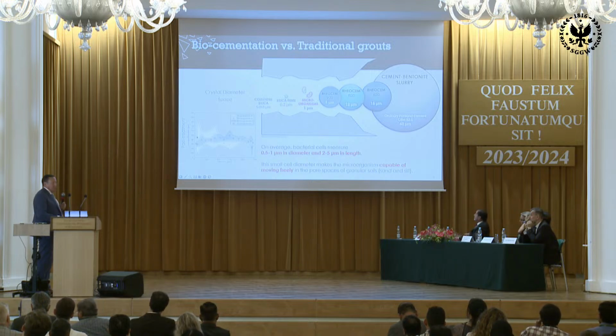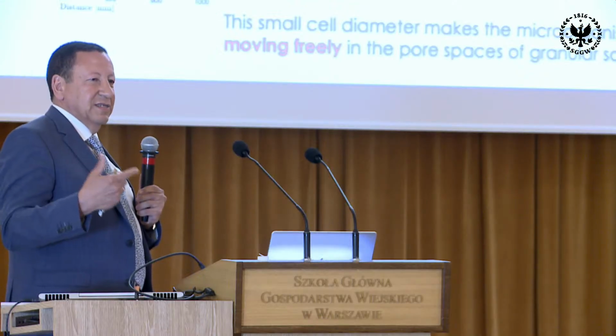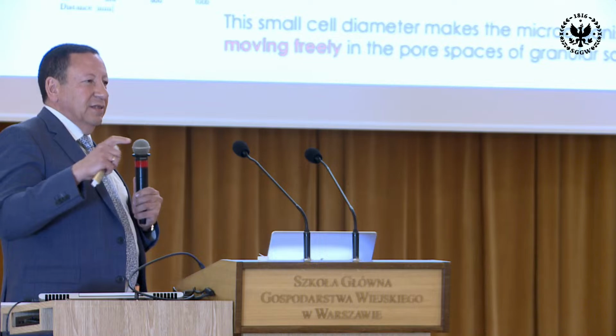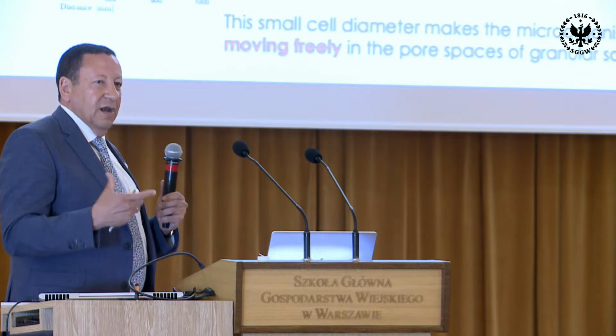So it means that we can inject something that is very fine, that is already covering part of the clays. So we can inject, of course, gravel, sand, silty materials, but also part of the clays. Then the point is that you inject this to fill the whole volume, because the idea is to fill as much as possible. What you see here in this curve is after the post-treatment, after the precipitation of the calcite. Starting from 1 micrometer, we get almost 80 micrometers of precipitated material. So we get something that is larger than the cement or the bentonite slurries in terms of size, so we can cover a large amount of volume.